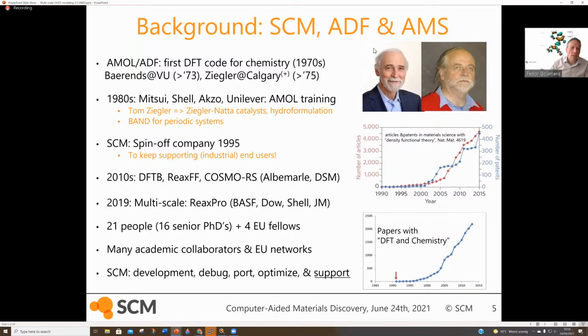So roughly 15 years ago, we also started implementing different methods. So away from density functional theory, going to less accurate but faster methods. So density functional based tight binding. There's reactive force fields. Together with Albemarle and DSM in the Netherlands, we implemented our version of COSMO-RS, which is a continuum based method using activity coefficients you get essentially from DFT calculations that allows you to calculate thermodynamic properties in solution.